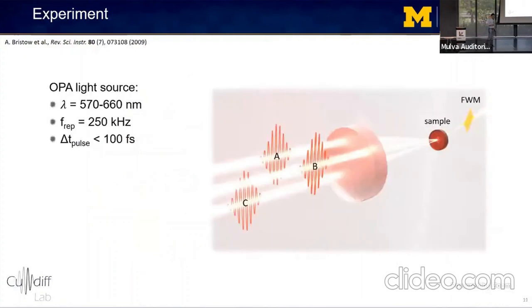And this is just a quick overview of our experimental setup. Our excitation pulses are focused onto our sample in the boxcar geometry, which results in a photon echo four-wave mixing signal being emitted in a unique direction. Our excitation pulses are generated by an OPA, tunable from roughly 570 to 660 nanometers at a repetition rate of 250 kilohertz. And the pulse duration varies a bit with the excitation wavelength, but is roughly 100 femtoseconds or below.